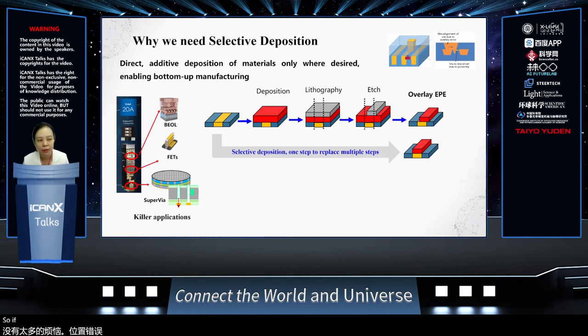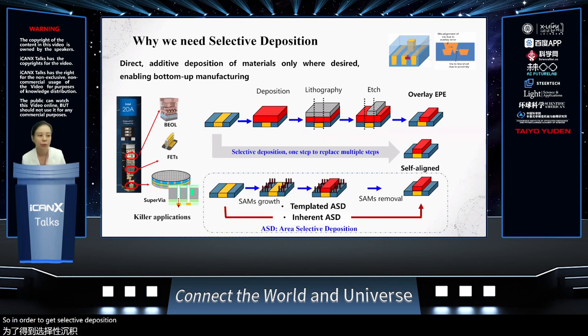So in order to get that kind of selective deposition, we regularly have two main approaches. One was actually developed a while ago, while I was a PhD, where we apply what we call self-assembled monolayers, this kind of inhibitors, selectively on certain areas, and then leave the other places to be able to selectively deposit. And now we are more focused on understanding the surfaces to give inherent ASD growth.